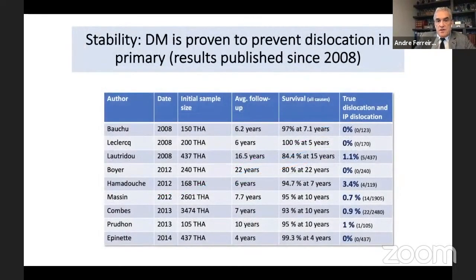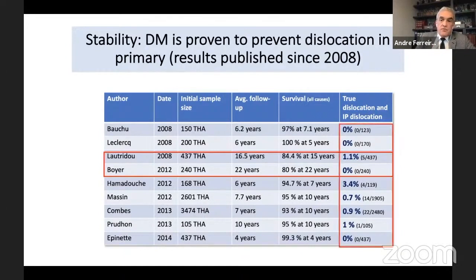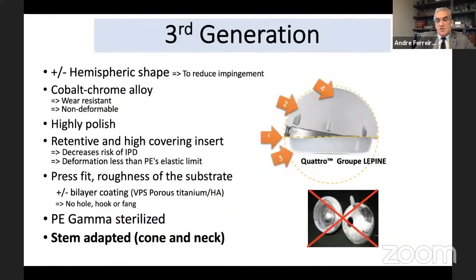So dual mobility is proven to prevent dislocation in primary, and we can see that in the first generation, results were very good with a very long-term follow-up. But for all the generations, results are similar, from 0 to 3% of dislocation according to the authors. The third generation, the contemporary one, has changed the design.